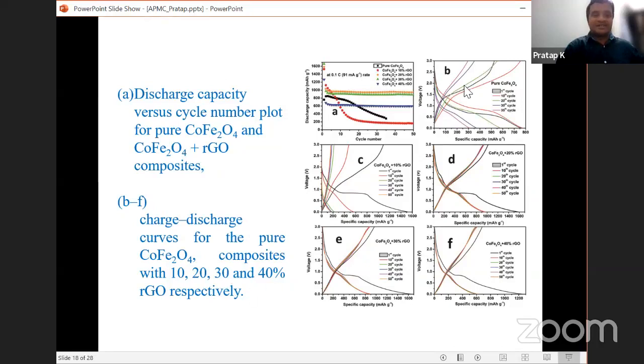So these are the charge discharge curves for pure cobalt ferrite, 10% RGO, 20%, 30%, and 40%. Look at this cobalt ferrite with 20% RGO. They are very clear. And you look at the voltage, 2.5 volts, and the specific capacity is gradually. This one.